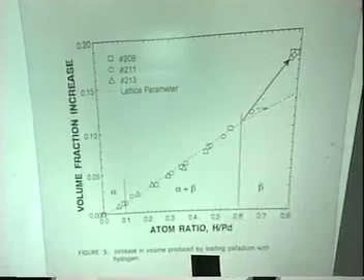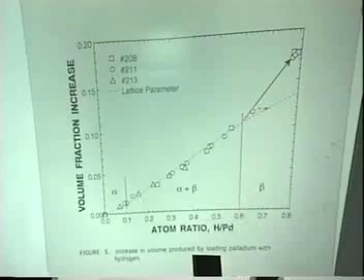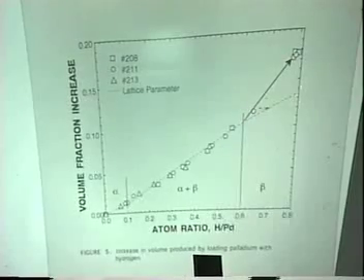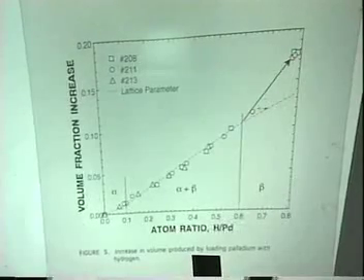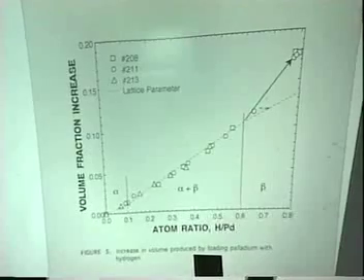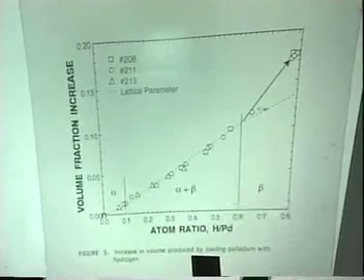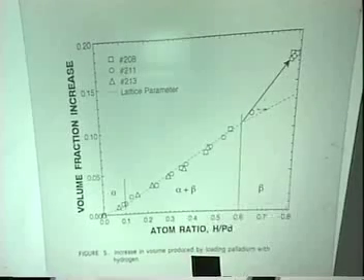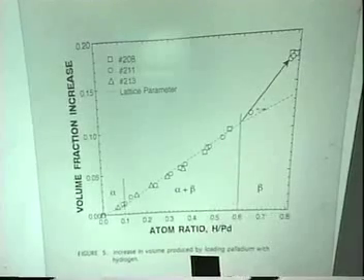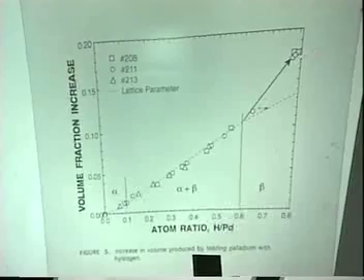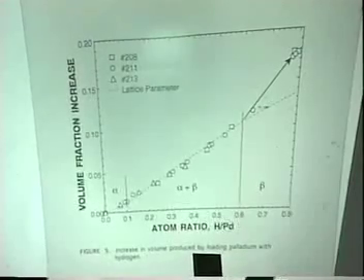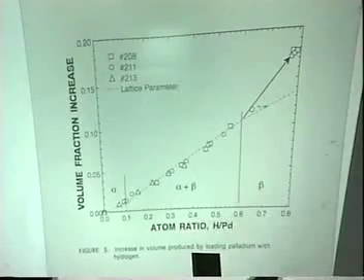And then the lattice parameter increase shows that it should do this, whereas the physical measurement shows that there's an extra volume being generated. That extra volume is caused by the cracks. So that's sort of the average effect of these cracks. It turns out, and you'll see a little later the importance of this, that most palladium cracks. And every time you go through this cycle, you get more cracks.